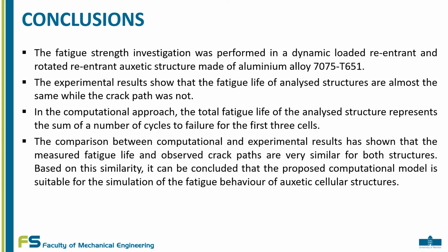In the computational approach, the total fatigue life of the analyzed structure represents the sum of the number of cycles to failure for the first three cells. For each of the three cells, the number of cycles to failure was calculated separately. For the next cell, the seam between neighboring cells is considered during the further computational analysis.